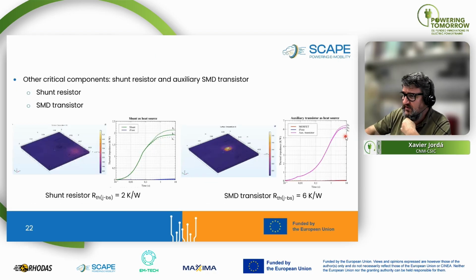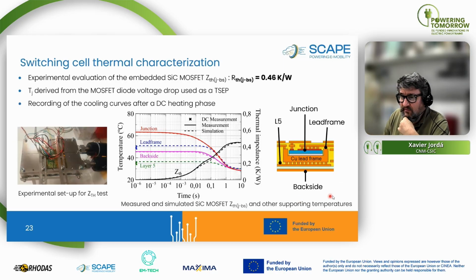Other critical components can be power devices placed on top, the shunt resistor. In any case, we have identified and we have been able to design the switching cell with relatively low thermal resistance values. These simulated values have been validated by experimental characterization of the switching cells. We used a standard thermal impedance measurement setup where the PCB is placed on a hot-cold plate, and we estimate the junction temperature of the power MOSFETs by using a thermosensitive electrical parameter.